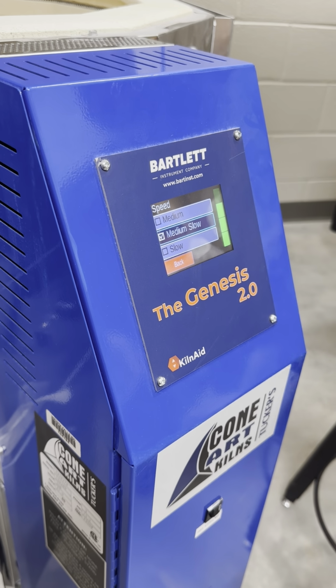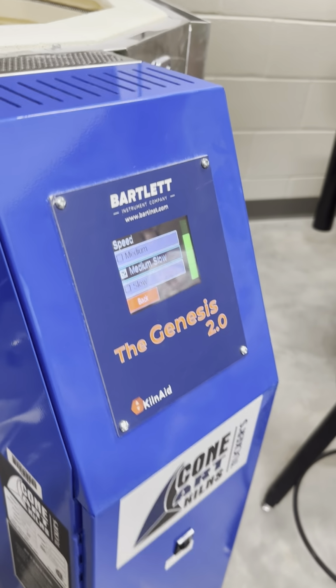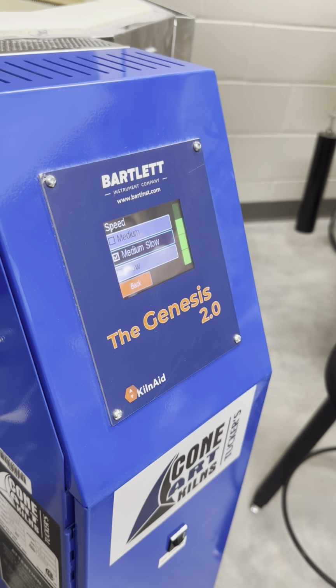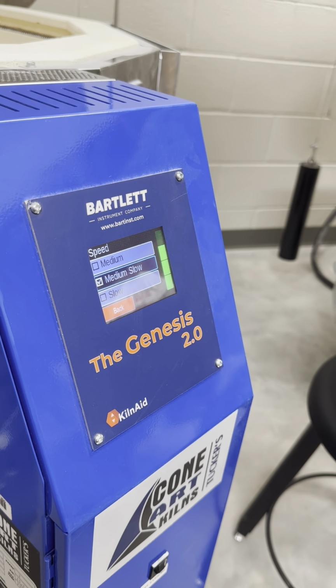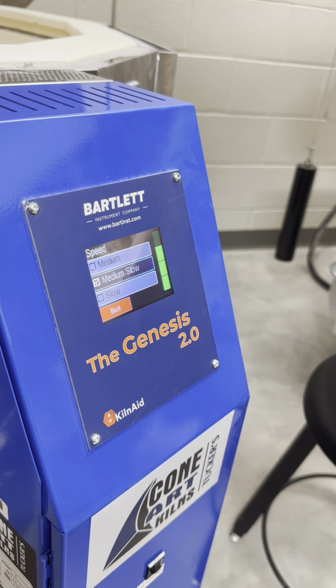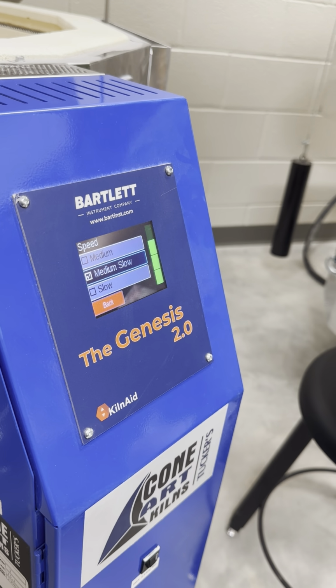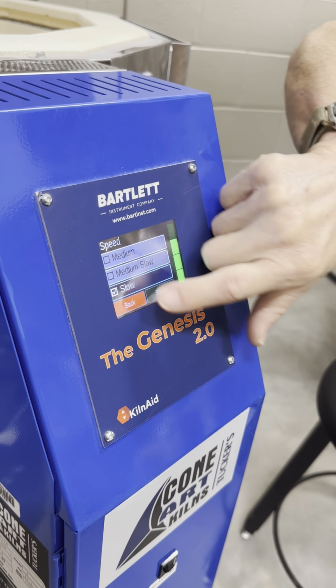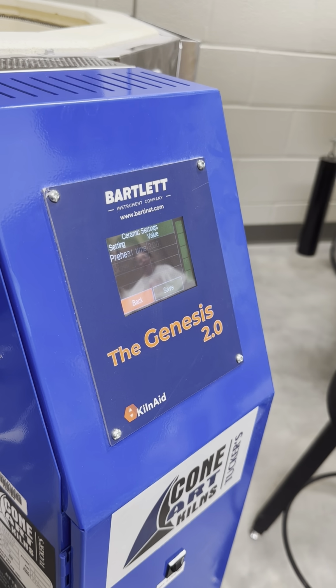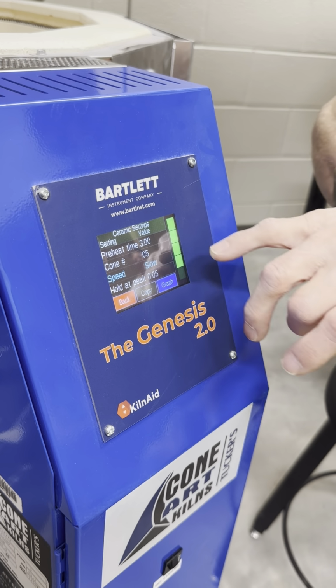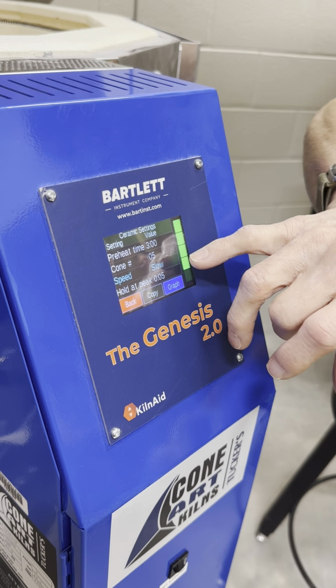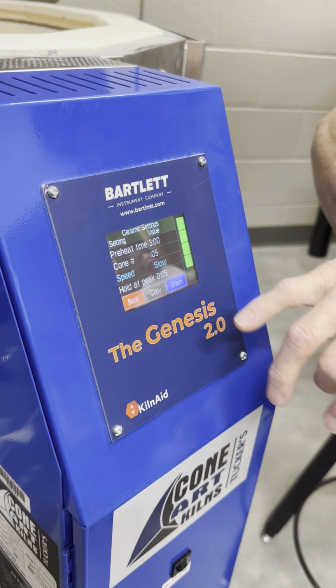But at the same time, if you're not quite sure, let's say you have some pieces that are a little bit bigger. You might have a sculpture that's this big, that instead of being that thick, it's this thick. So then what we might do is put it on slow. And so now we're at a preheat time of 3 hours, cone 05, it's on slow. We're gonna hold it at the peak.